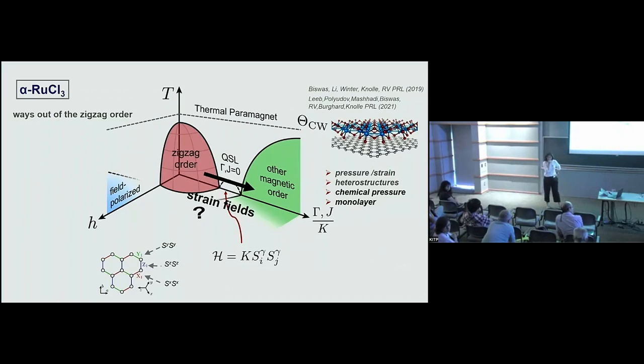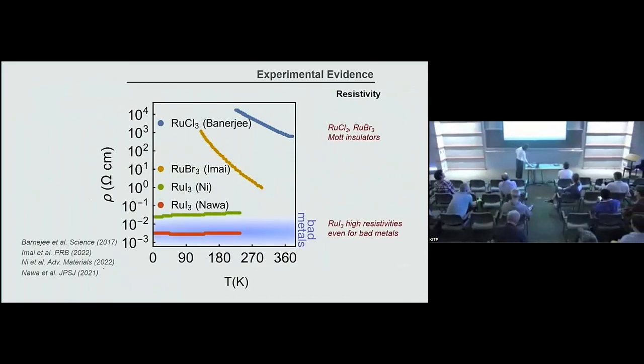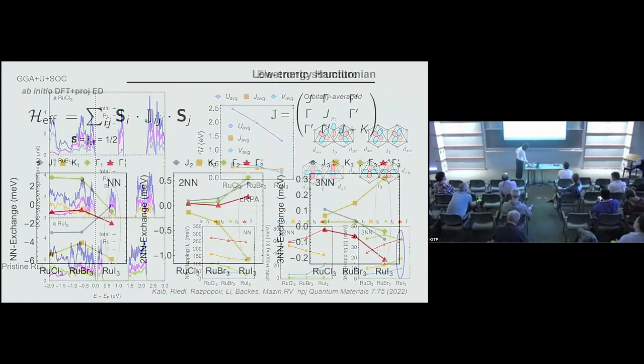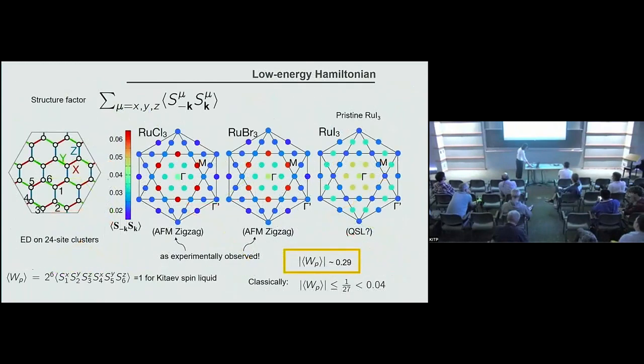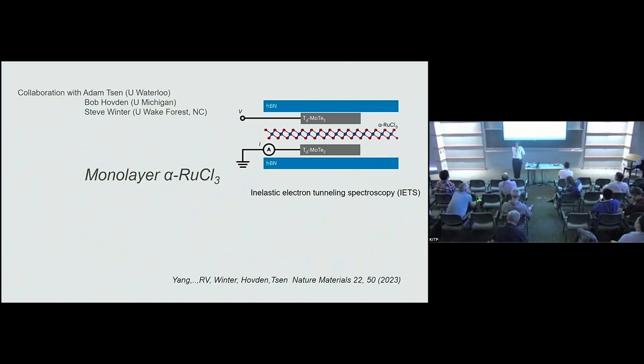My question is about the change in anisotropy you show in the case of the ruthenium chloride heterostructure, that it can occur in proximity. In the monolayer. Yes, here in the monolayer. So there is a way to change anisotropy in proximity of a metallic system. Would that be possible also in the iodine system, if it's more metallic?